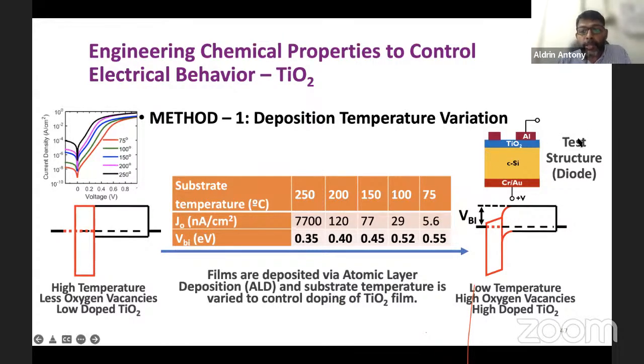So this was the test structure, and this was the built-in potential. And you could see this is the conduction band here, right? So at low temperature, what we expect is we could see high oxygen vacancies formed. When oxygen vacancy is formed, this material will become more and more N-type. So the Fermi level will go up, so that this difference VBi will start increasing. That is what we are expecting. If we increase oxygen vacancies, we could increase the built-in potential.